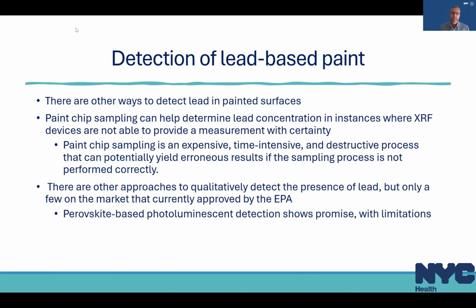So there are other ways to detect lead in painted surfaces. One of them is paint chip sampling, which can be very precise, and it can help determine lead concentrations when you can't use an XRF device or it's not appropriate to use an XRF device. I will caution that paint chip sampling is expensive, time-intensive, and destructive. And if you don't do it right, you don't take down to the bare substrate, or if you include substrate, you may yield erroneous results. So it is a very specialized thing to do, paint chip sampling, and as a result, we don't generally perform paint chip sampling as a way to determine the presence of lead-based paint.